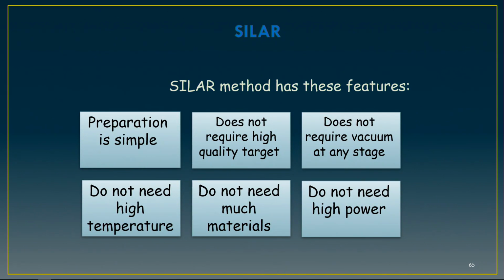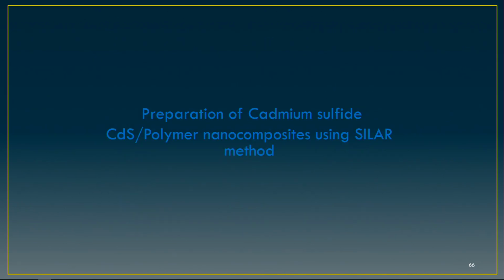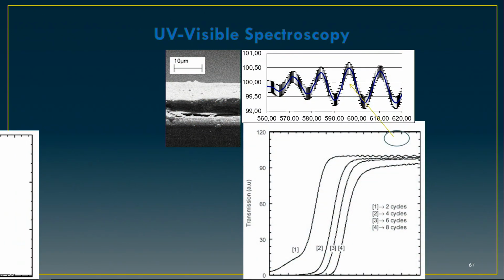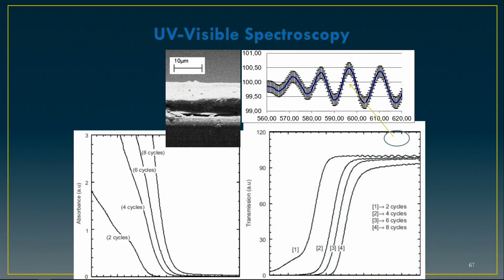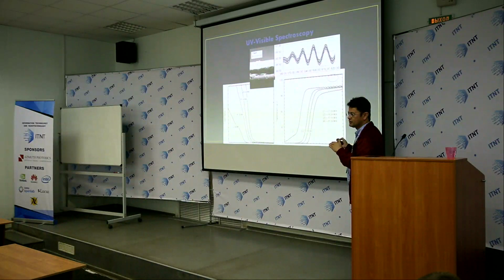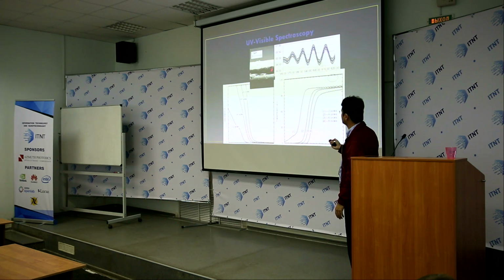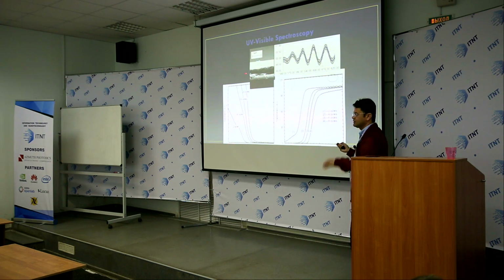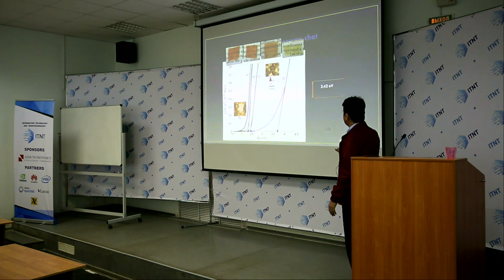These are the results, the spectroscopic results: wavelength, absorbance, transmittance. There is an interferometric pattern here. We can calculate the film thickness using this interferometric pattern. And also we have here the film thicknesses using a cross-sectional scanning electron microscope. Then we calculated the band gap of the semiconductor using these techniques. These are the real polymer nanocomposite materials which we have prepared.